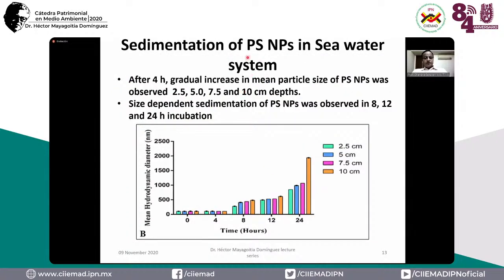Once again, sedimentation of polystyrene nanoparticles in seawater. We did an experiment with seawater; the previous slide was on lake water. After 4 hours, a gradual increase in particle size of polystyrene nanoparticles was observed, at 2.5, 5.0, 7.5, and 10 centimeter depth. So we could see that along the depth, there was an increase in the particle size of the nanopolystyrene. That means the natural colloids are more in the bottom layer compared to the top layer of the system.